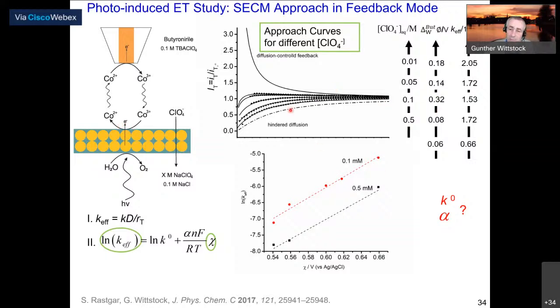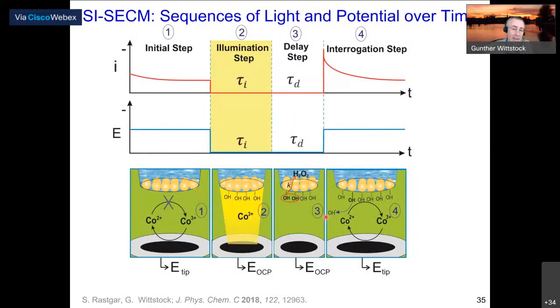And the rate depends on the polarization which we induce by different compositions of the electrolyte. In a very systematic way, we can construct something like Tafel plots for that rate constant. And again, we can make these pulsed experiments where we illuminate the nanoparticles, wait a time, and then interrogate what has happened.